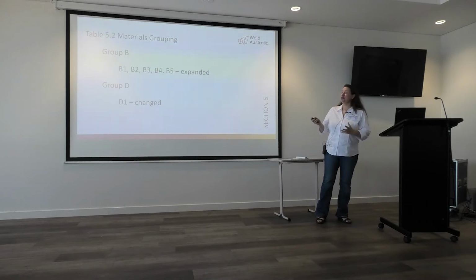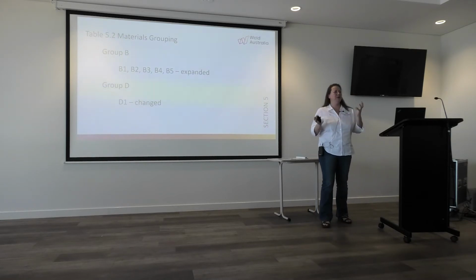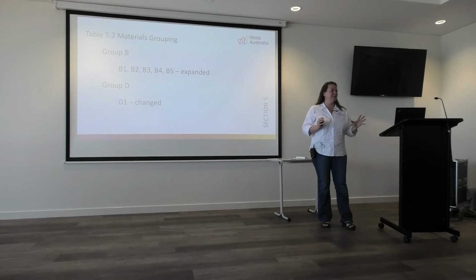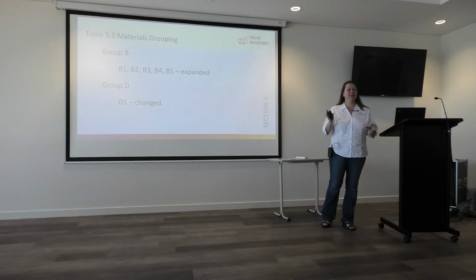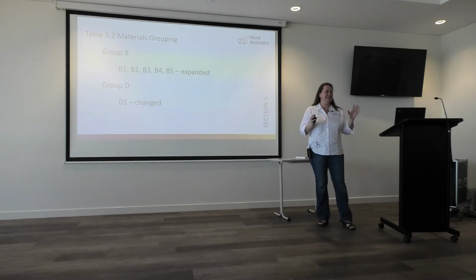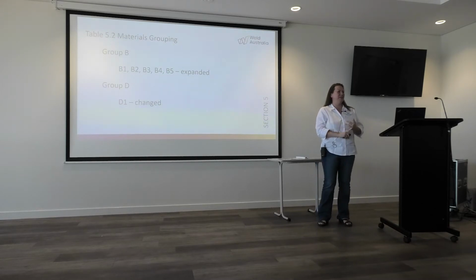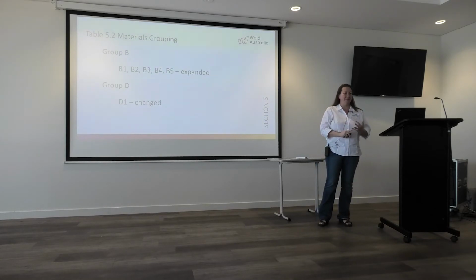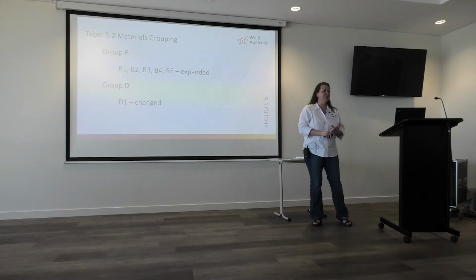And then materials grouping, we've got a bit of an eclectic way of doing materials. So carbon steels are basically group A, B was just a bit of moly added, and then C was P11, and D had your D1 was chrome moly vanadium, but D2 is chrome moly, D3 is chrome moly, and then D4 is chrome moly vanadium.